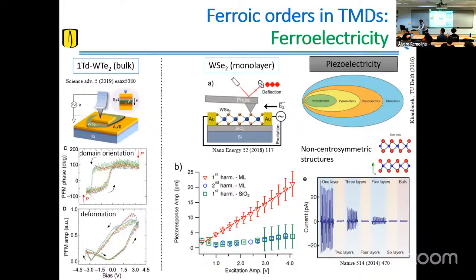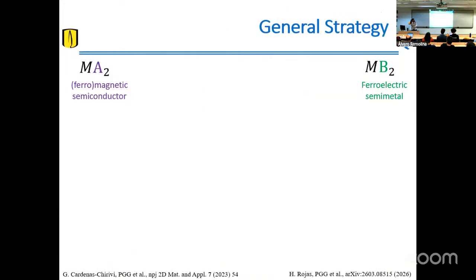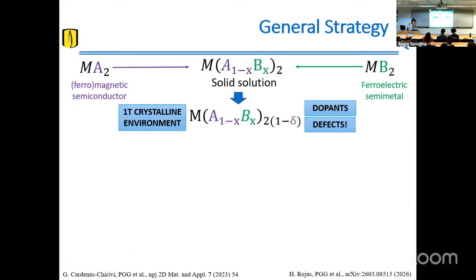Okay. This effect is caused because in an odd number of layers, the crystal structure is non-centrosymmetric, which seems to be a key component for the ferroelectricity in these materials. But this only happens in the nanostructure. So what we have been doing is trying to promote the presence of these ferroic traits through solid solutions. The creation of this solid solution has all three components that I talked to you about in terms of the ferromagnetism.